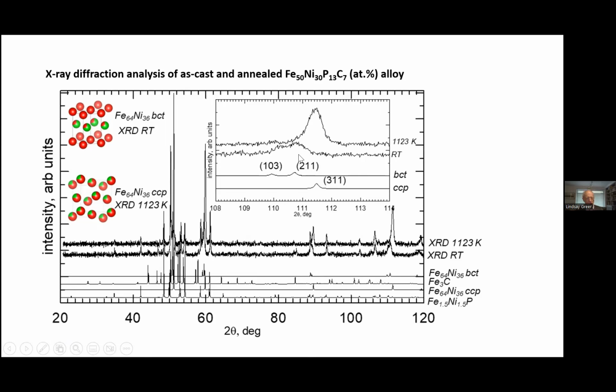Life is not simple, however, because you can get this type of splitting by superimposing X-ray peaks characteristic of different crystals in the material. We have a number of different crystal phases present. So it's fair to say that the interpretation of this is not unambiguous, but at least there was a suggestion that we had tetrataenite.